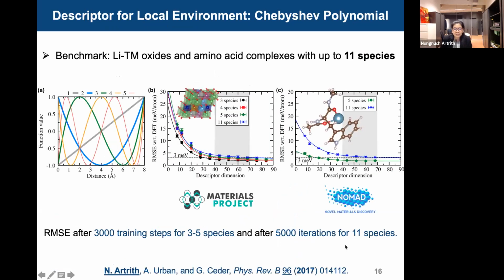So we did some tests, and this slide shows the benchmark of the Chebyshev descriptor, which can be used for any number of chemical species with the same efficiencies and also high accuracy, like you can see here. So in these figures, we take the database from the Materials Project and we test our descriptors. The x-axis is the descriptor dimensions, from 10s until 90s. And the y-axis shows the root mean square error, RMSE, that the neural network potentials predict against the reference data as DFT.